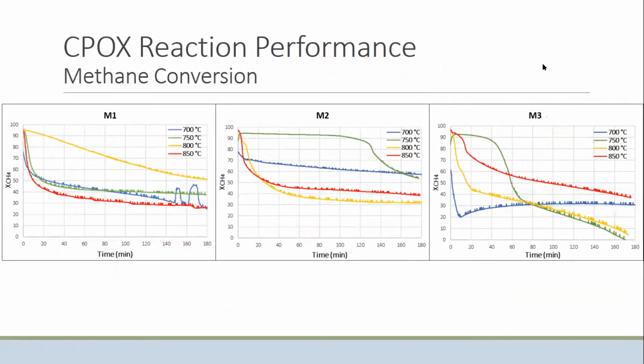This graphic represents the results of the partial oxidation reaction for each catalyst. According to the graphs, the optimum temperature for the reaction is for the M1 catalyst 800 degrees, for M2 750 degrees, and for the M3 catalyst 850 degrees. Also, we can specify that increasing the content of molybdenum lowers the stability of the catalyst,